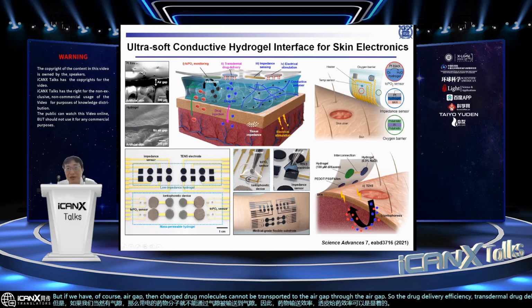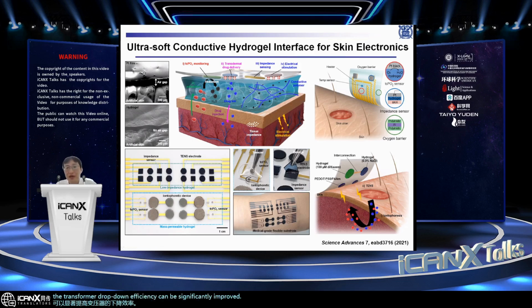But by using the hydrogel layer, since the hydrogel contains water, charged drug ions can be easily transported following the applied electric field. So the transdermal drug delivery efficiency can be significantly improved. Also, by adding conducting filler like PEDOT:PSS conducting polymer, the ultra-thin hydrogel layer can have high conductivity and low impedance, and therefore the sensing quality of the impedance sensor and the stimulation efficacy of the electrical stimulator can be improved significantly. So by simply adding a very thin, ultra-thin conductive hydrogel layer, all the sensing and feedback therapy quality can be significantly improved.